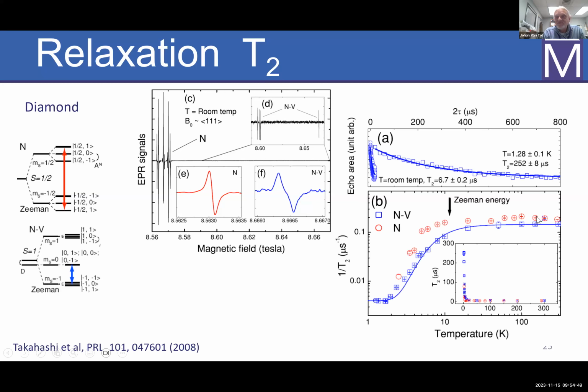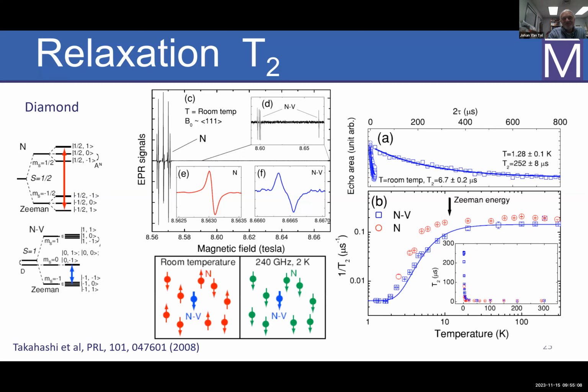And indeed, if you go to the low temperature limit, you can see that the T2 gets much longer. And this simple model seems to fit quite well. So for these concentrated systems, the T2 gets a little bit longer, and this is kind of the simple model.